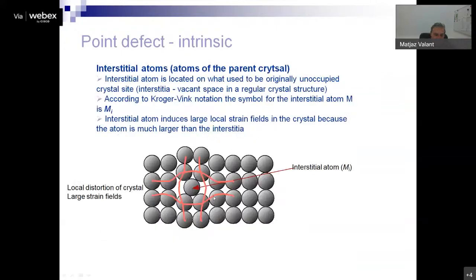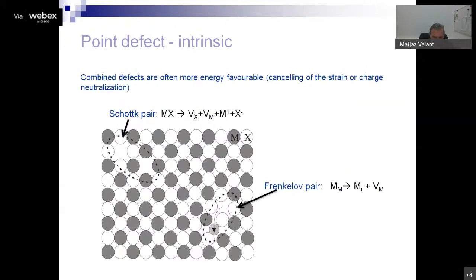Now these large strain fields are not very favorable for the crystal system. It highly increases the energy of this system. So the crystals invented a mechanism to reduce this strain field. And this is done by combining different defects in one structure. So one possible combination is, when we talk about vacancies, that in addition to removing anion, we also remove cation. We would have two vacancies, but the strain field would be significantly reduced. And this is quite often the case in ionic crystals. And we call this kind of situation a Schottky pair.